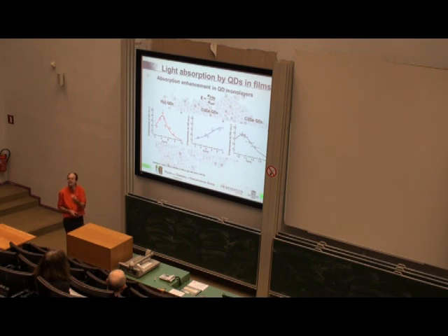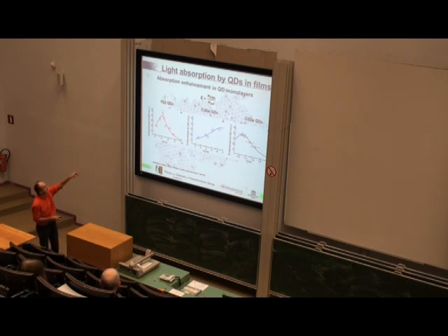What we change is the diameter of the quantum dots. We have different measurements for different sizes. The vertical axis gives this ratio. And what you see is that when you assemble them in a film, the very same quantum dot will absorb 2 times, 3 times, up to 5 times more light than when it's just in solution. And this is something that apparently depends also on their diameter. There's a kind of optimum diameter. In the case of lead sulfide, this is 4 nanometers. In the case of cadmium selenide, you see the same thing. Packed in a film, they become stronger absorbers. Again, an optimum, in this case, somewhere around 6 to 7 nanometers.